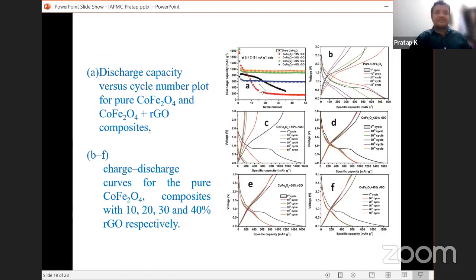So this is about discharge capacities: discharge capacity with cycling number, and specific capacity with voltage. What is happening is that this is the discharge capacity. Discharge capacity means that we apply 0.1 ampere of current and we observe the charging. After that we leave it and we see how it is discharging. So if you look into this diagram,